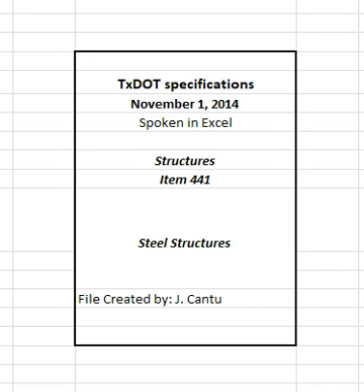Ensure painted faying surfaces meet the required slip and creep coefficients for bolted connections as outlined in DMS 8104, Paint, Shop Application for Steel Bridge Members. Use a Class A slip, minimum slip coefficient of 0.33, if no slip coefficient or corresponding surface condition is specified. Perform all required testing at no expense to the department. Surface preparation and painting the interiors of tub girders and closed boxes is in accordance with DMS 8104, Paint, Shop Application for Steel Bridge Members.